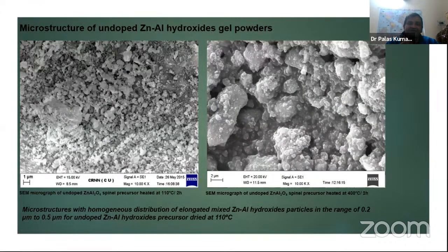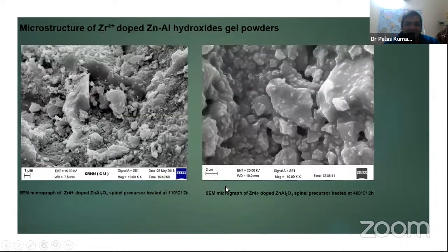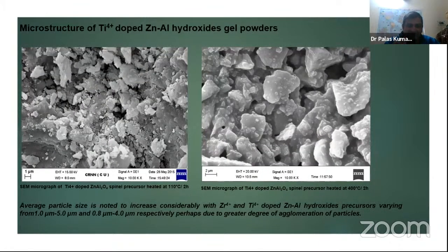subsequent slide. Now, if we see the microstructure of undoped zinc aluminate hydroxide gel, on the left hand side you see the heat treated at 110 degrees, and the right hand one is the 400 degrees. Yes, due to heating at high temperature, obviously the particle size will be higher. And if we see the zirconia part, this is the titanium, and it is quite clear that the particle size is increased with zirconia and titanium doped hydroxide matrix, which is perhaps, of course, due to agglomeration of the particles. This is needless to explain.